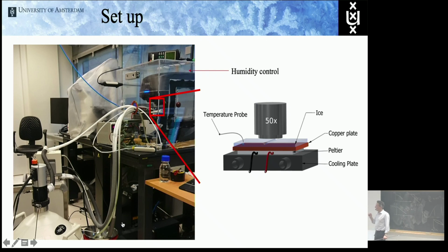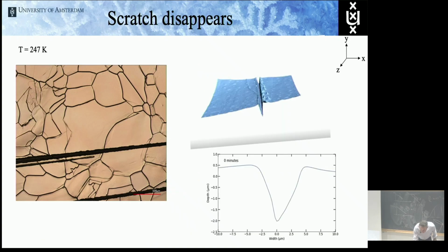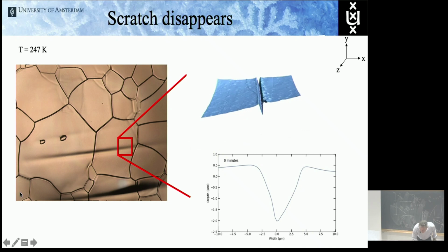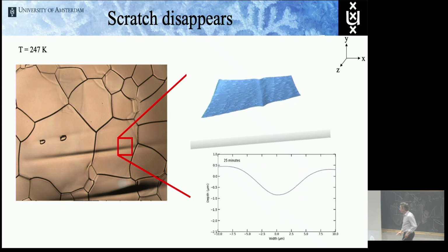With a very thin razor blade, he makes these scratches. And so this is the better measurement, where you can see quantitatively the surface with the scratch. You can see the scratch before and after disappearing, and quantitatively you can average over this direction, and then you get an average profile.